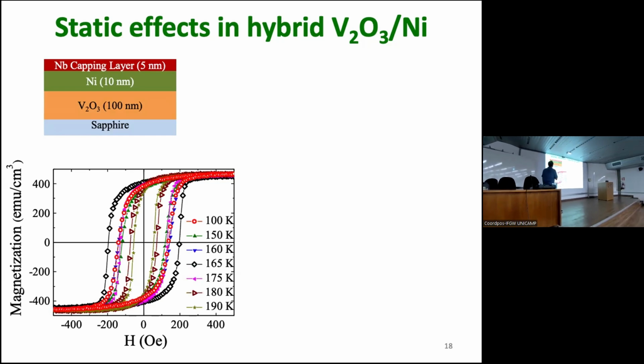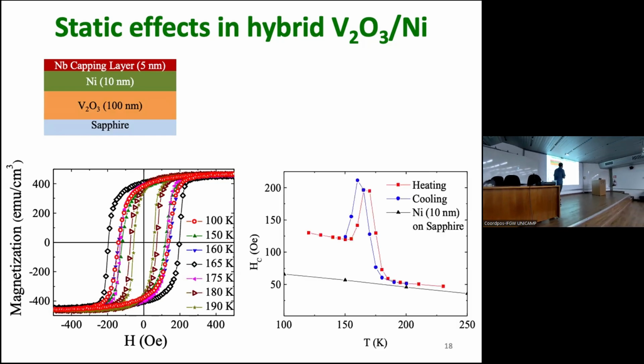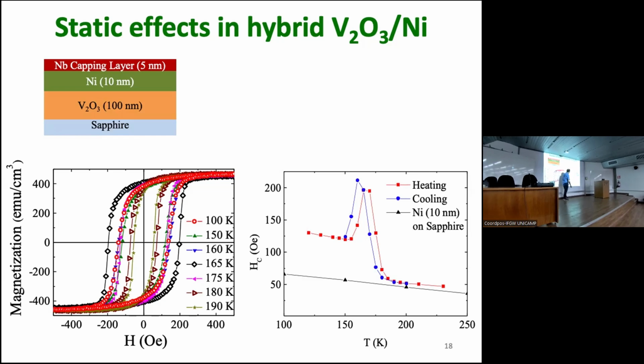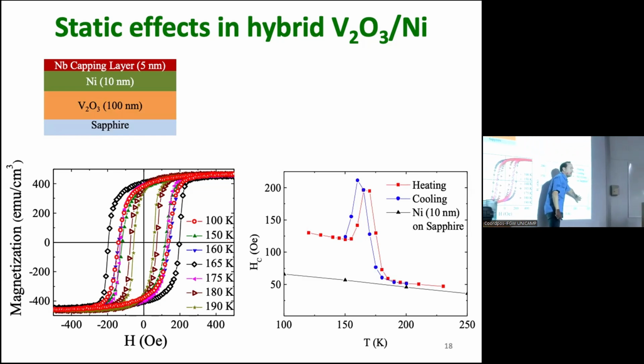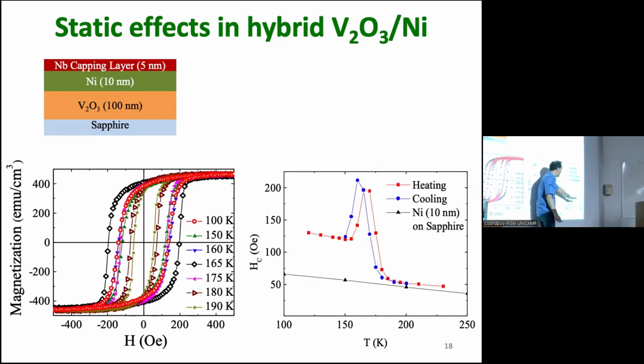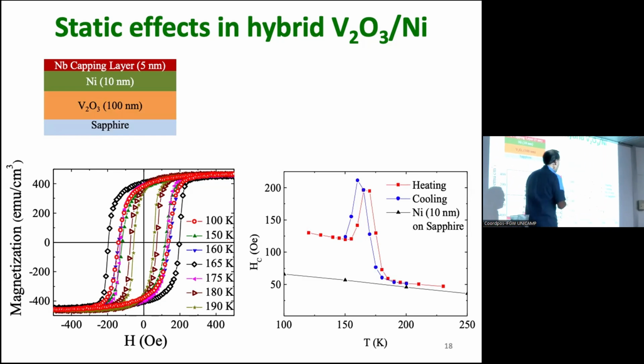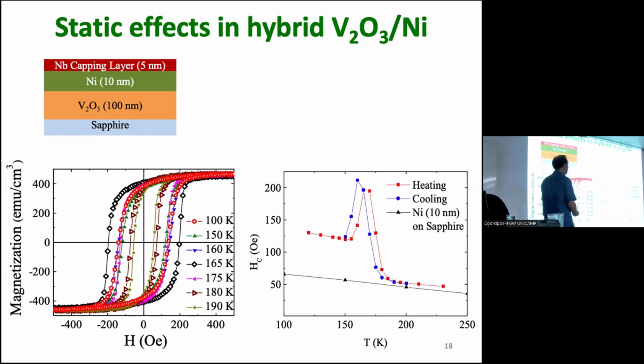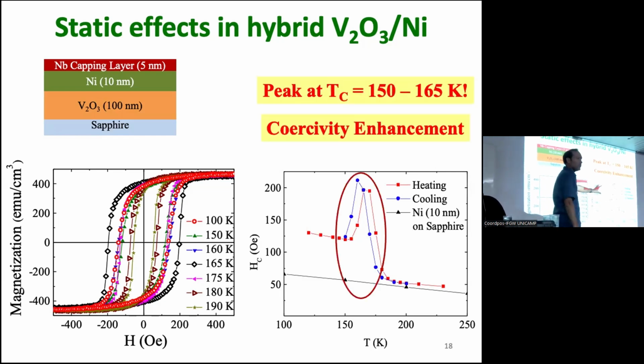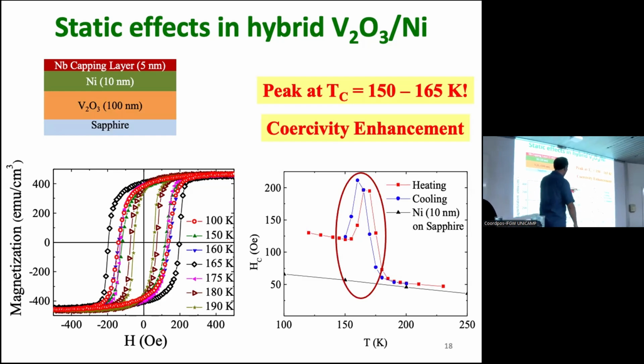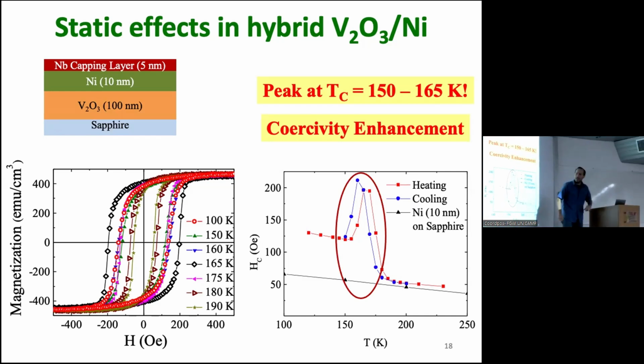And that in principle doesn't make sense because nickel by itself doesn't do that. We actually compare the coercive field with just nickel. So this is the nickel, it's a straight line, and this is the heterostructure that I just showed. So quite different. They are only similar at high temperature, and this is because we grew the nickel on top of this material at room temperature. So you have a 300% change. And this is very useful. We wrote a couple of patents just thinking about how to use this for something useful. And I can talk about that later.